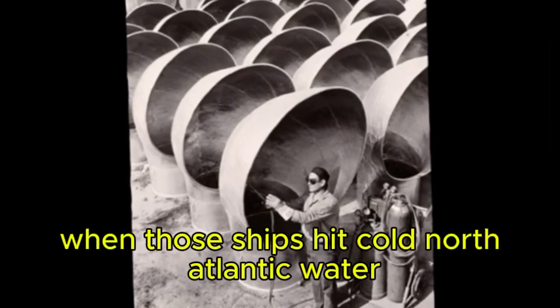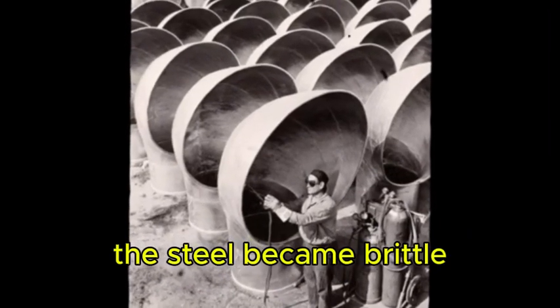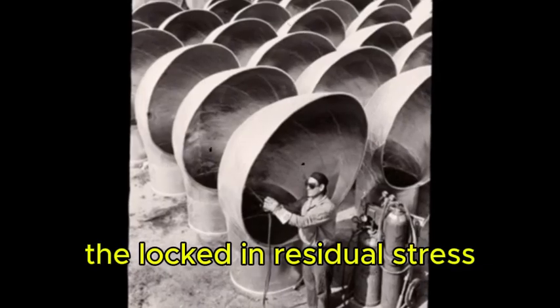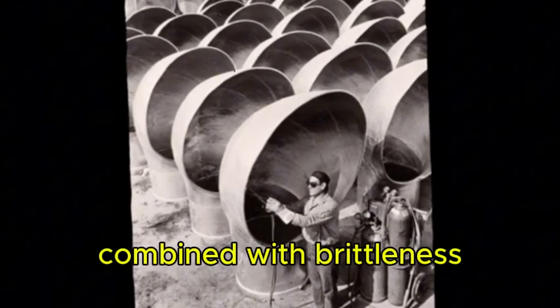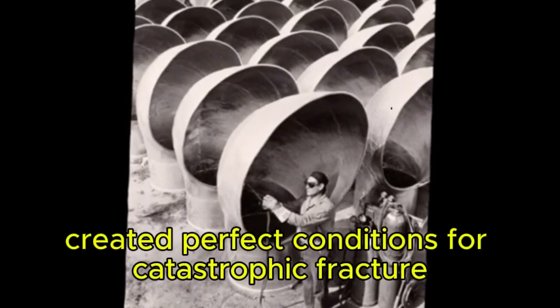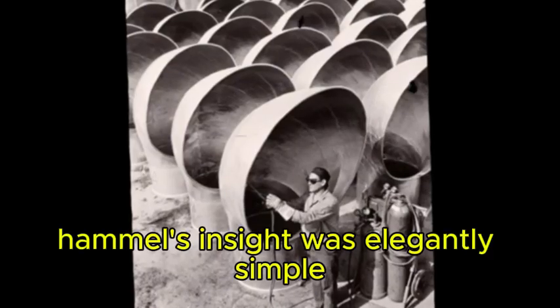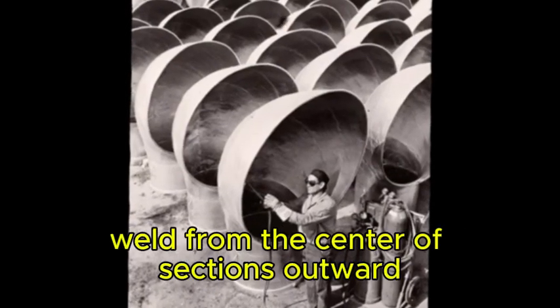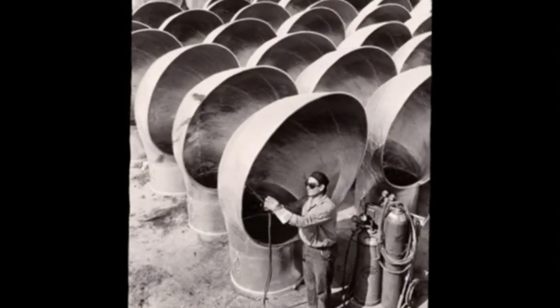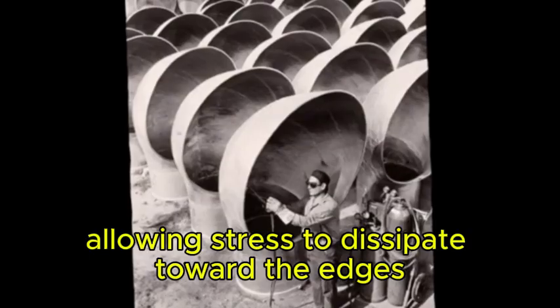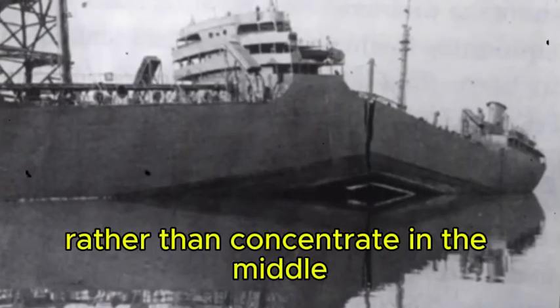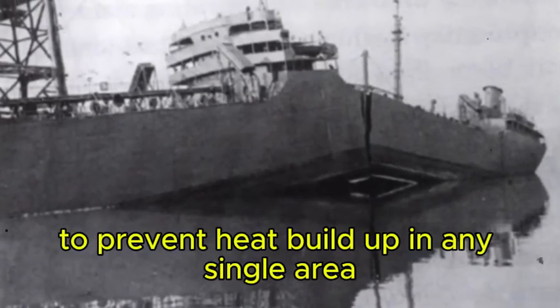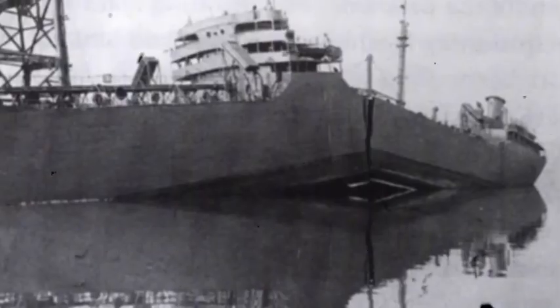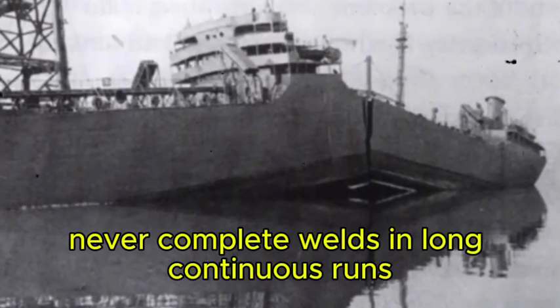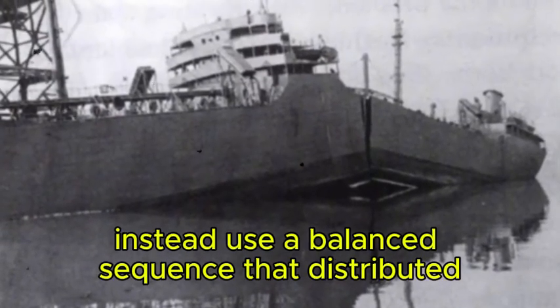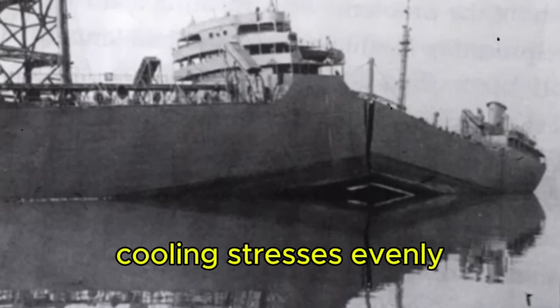When those ships hit cold North Atlantic water, the steel became brittle. The locked-in residual stress combined with brittleness created perfect conditions for catastrophic fracture. Hamill's insight was elegantly simple. Weld from the center of sections outward, allowing stress to dissipate toward the edges rather than concentrate in the middle. Alternate welding locations to prevent heat buildup in any single area. Never complete welds in long continuous runs. Instead, use a balance sequence that distributed cooling stresses evenly.